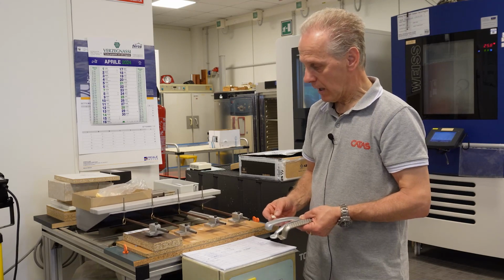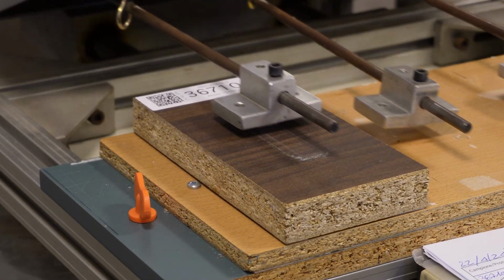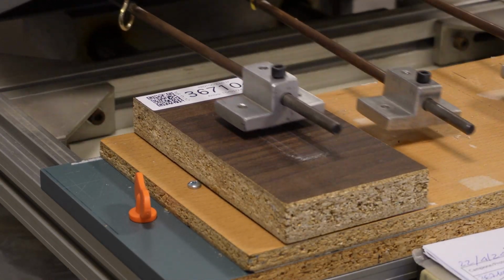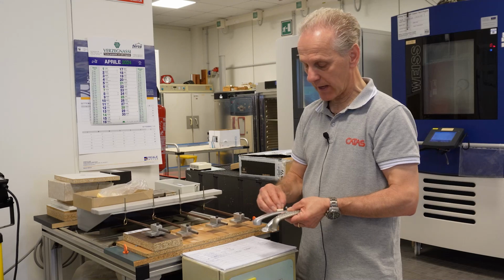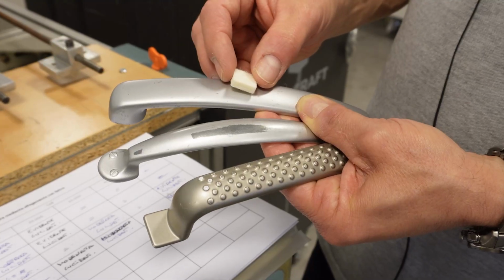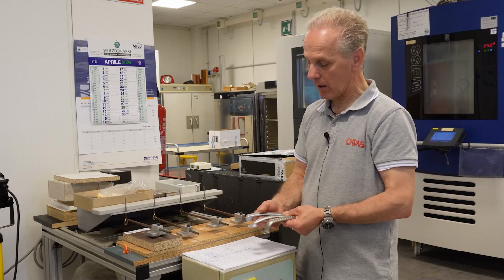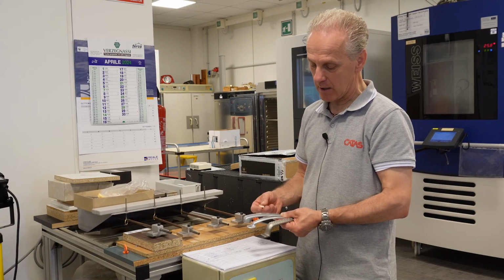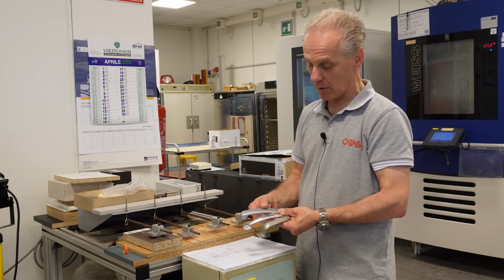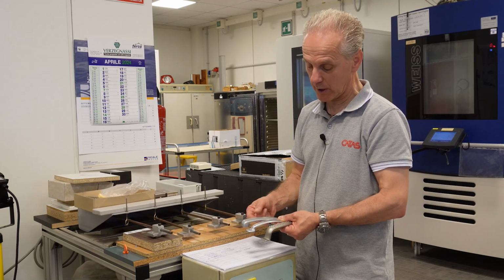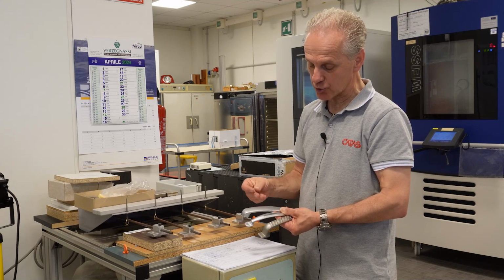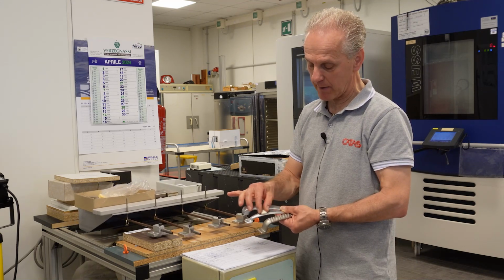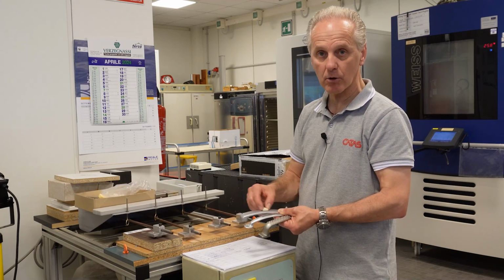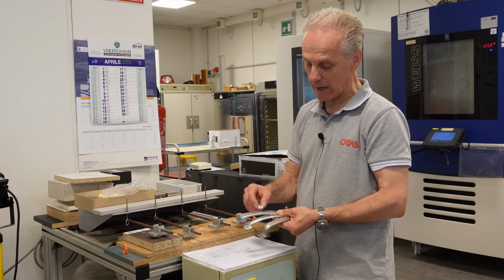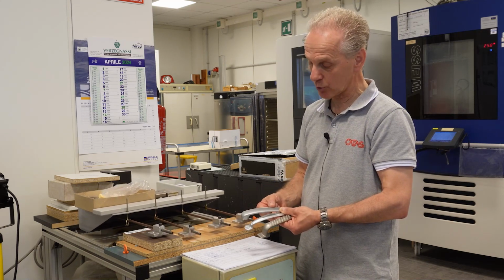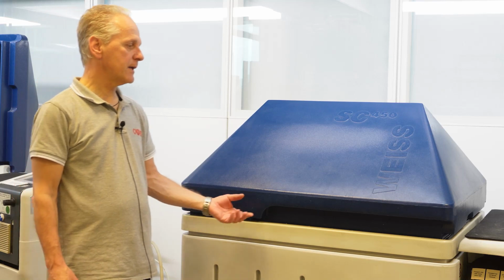This is a rubbing test. The rubbing test is performed by moving a swab of felt up and down. We rub it on the surface, and this test is useful to determine resistance in handles, for example, handles with galvanic coatings or with varnish finishes. And you can see this handle suffered damage through the rubbing test. The client then changed the varnishing cycle and was able to obtain a better performing resistance.